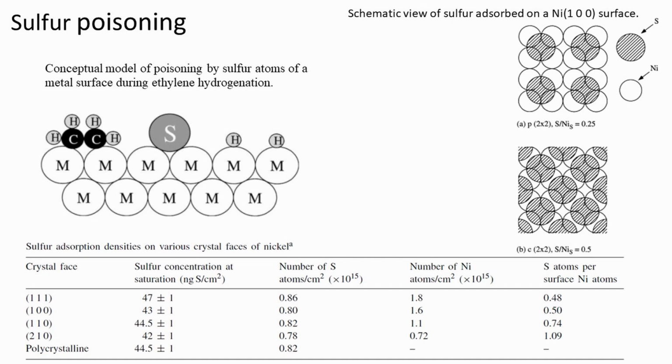Because the adsorption of sulfur components is generally rapid and irreversible, surface sulfur concentrations in catalyst particles and beds are non-uniform. H2S adsorbs selectively at the entrance of the packed bed and on the outer surface of catalytic particles, making the experimental study and modeling of sulfur poisoning extremely difficult.